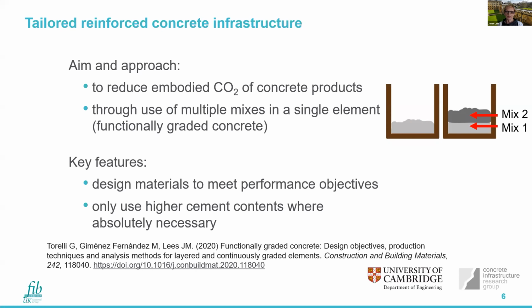One of the interests at the moment is tailored reinforced concrete infrastructure. What we're looking to do through our tailored systems is to reduce the embodied CO2 of concrete products. And we do this by using multiple mixes within a single element, primarily looking at wet casting. So this is functionally graded concrete, where we accept the idea of having more than one concrete mix within a single element. And why that's so powerful is we can now use that flexibility of concrete to design concrete materials to meet specific performance objectives, which may vary within an element or a structure itself. And really the overarching idea is to only use higher cement contents where absolutely necessary.